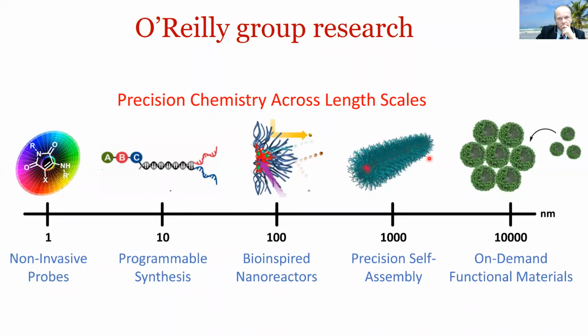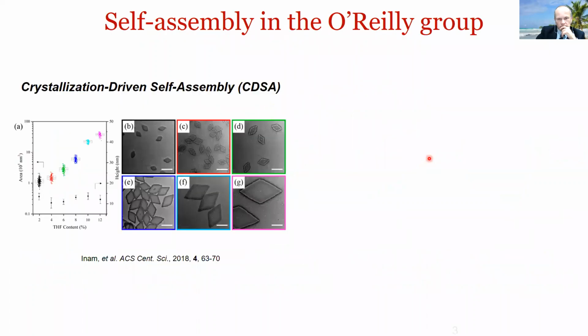So self-assembly is something that underpins all the work that we do in the group primarily, and there are two main elements of self-assembly that we're most interested in and have been in recent years. The first is crystallization-driven self-assembly, where we use a semi-crystalline block polymer, and we nucleate and then seed to create a seed from which we can, in a very controlled manner, grow these self-assembled constructs. Shown here are some of the diamond platelets that we were able to make, where we can quite carefully control both the dispersity and size of these constructs.